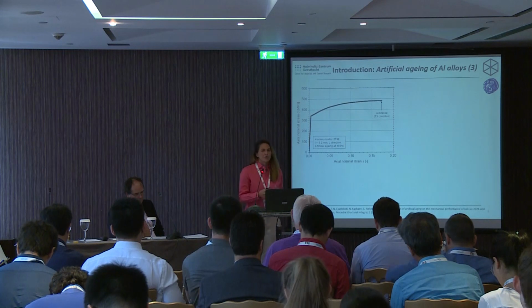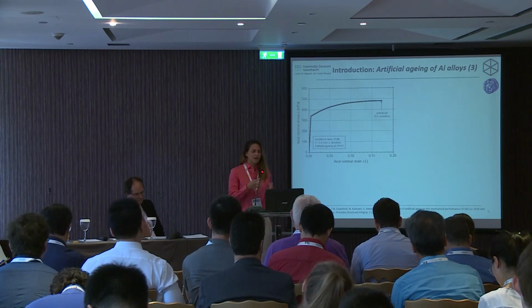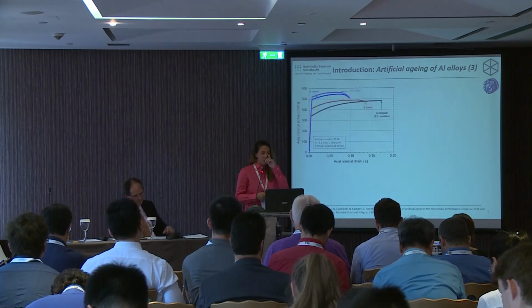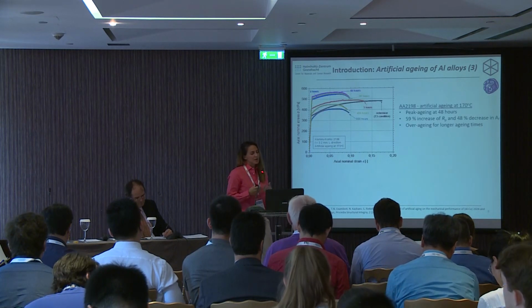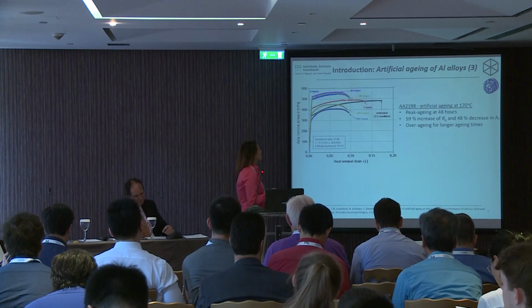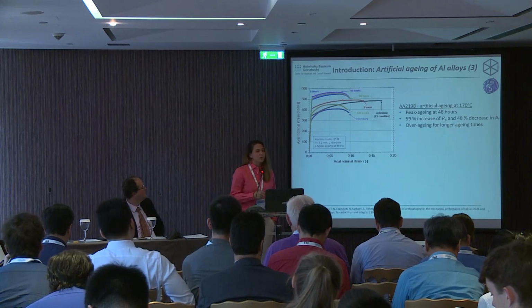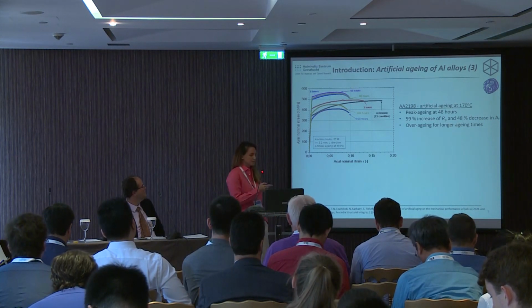Tensile mechanical behavior at various artificial aging times was examined in the literature. Here you can see that with increasing artificial aging, yield stress increases after 48 hours and elongation decreases.